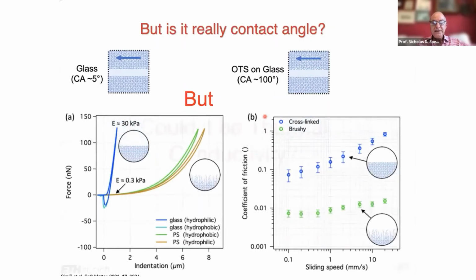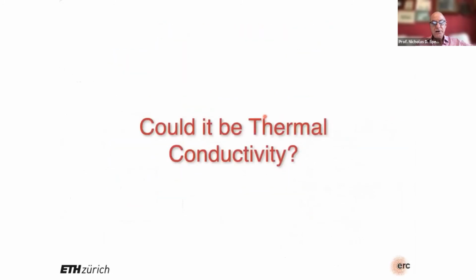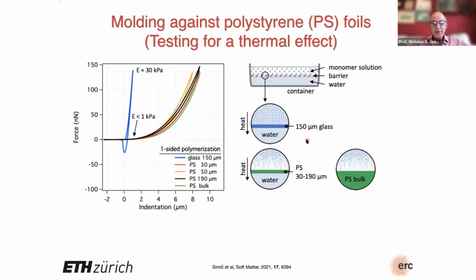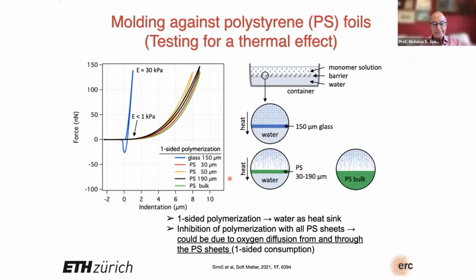So we started to look into other possibilities. Could it be thermal conductivity? The way we looked into this is we did one-sided polymerization against membranes above a water heat sink in order to maintain the temperature at the interface. And we found that irrespective of the thickness of the polystyrene, we saw no difference. This means that even though we were shielding this side more and more from the water, we really saw no difference. So it didn't seem like it was a thermal effect.